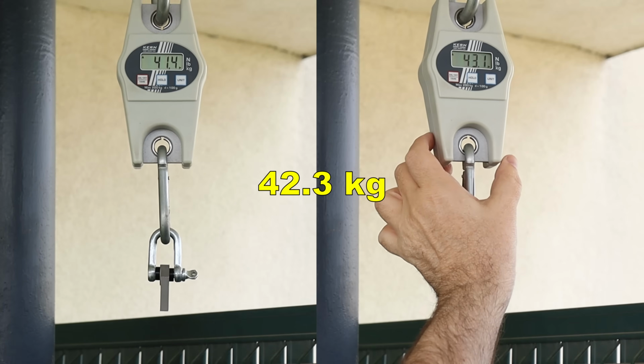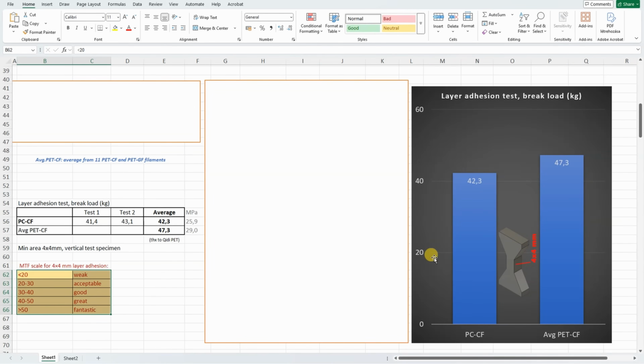Layer adhesion, vertically printed specimens. Not bad. This is my table with the rating for this test object. And we can see that these filaments have a great layer adhesion, just a little bit weaker compared to the average PET-CF, but this is very good too.